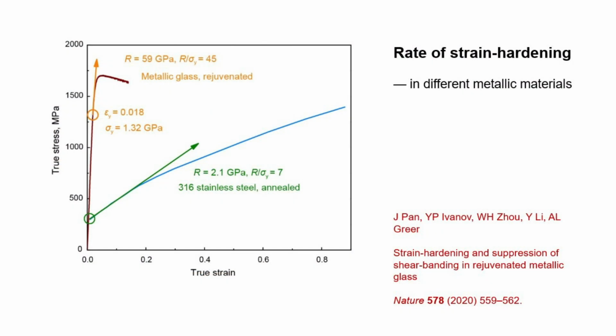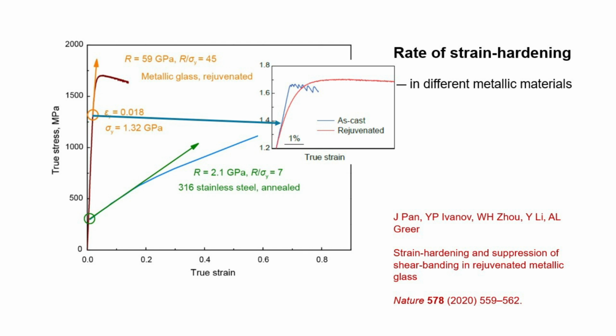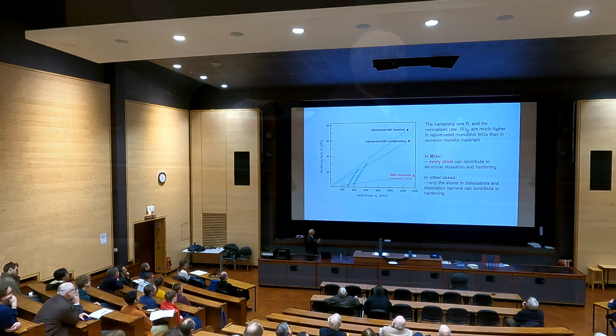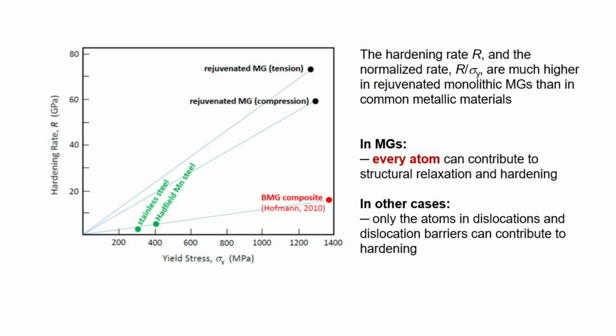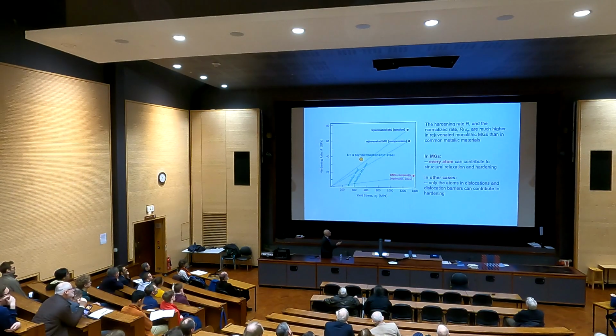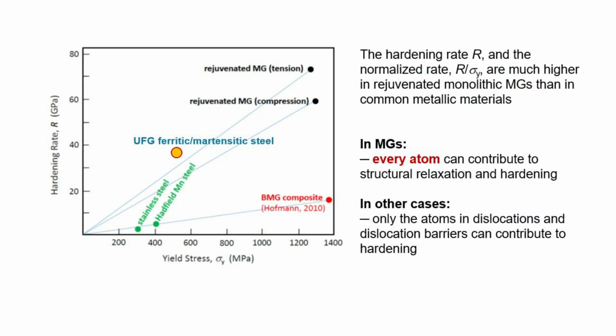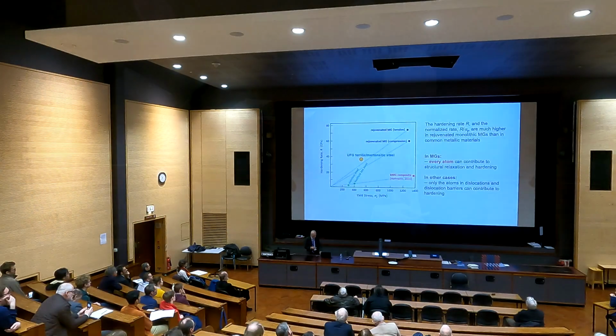The material does get harder, and you could ask, well, how fast does it get harder? It's hard to see the onset of plastic flow here, but it is here. And the answer is that it gets much harder very fast. Much harder than many conventional materials. This is an ultra-fine-grained steel, which is roughly competitive. Why does it harden so fast? Possibly because every atom in that structure has its little job to do in making the material harder, unlike just those at dislocations. This is the hardening rate.